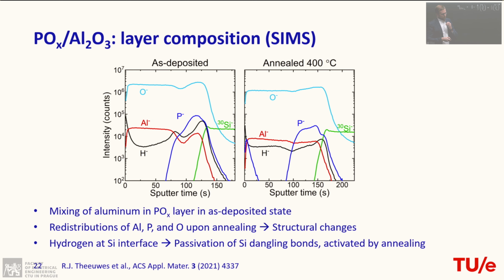If we then try to understand a little bit more about the layer composition with SIMS, we see that aluminum is actually mixing into my phosphorus oxide layer already in the as-deposited state, as you can see here. If you go for some annealing, as we've done here, we see that the distributions actually mix a little bit. So you redistribute your aluminum, phosphorus, and your oxygen. Structural changes must be there. And also hydrogen, which you cannot detect so easily in this way, although you see differences there too, must also reach this silicon interface. So we hope that we passivate our surface dangling bonds in this way.